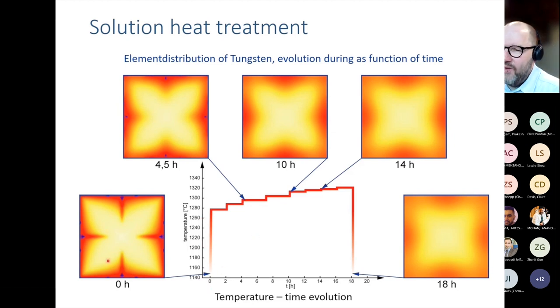So going up, this is initially our as-cast structure. Here we're looking at the tungsten distribution, ramping up through a number of steps. After 4.5 hours, we find some diffusion going on. We homogenize it slightly. The gamma prime is still present. After 10 hours, the gamma prime is gone, and then diffusion continues to homogenize the material.